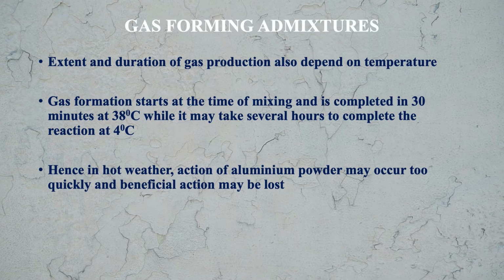Hence, in hot weather the action of aluminium powder may occur too quickly and its beneficial action may be lost. What is the meaning of this? Because in hot weather the gas formation will be done very quickly, but it may be lost before the concrete is used, in the sense that placement and compaction is done.